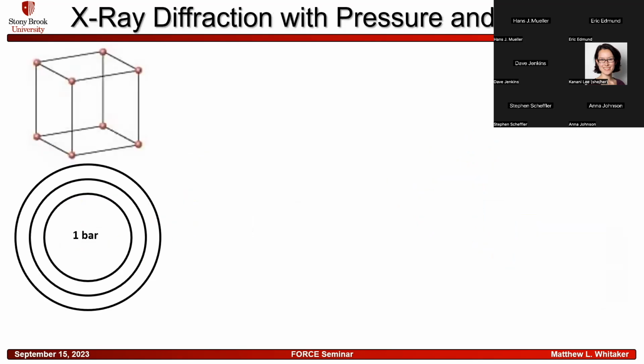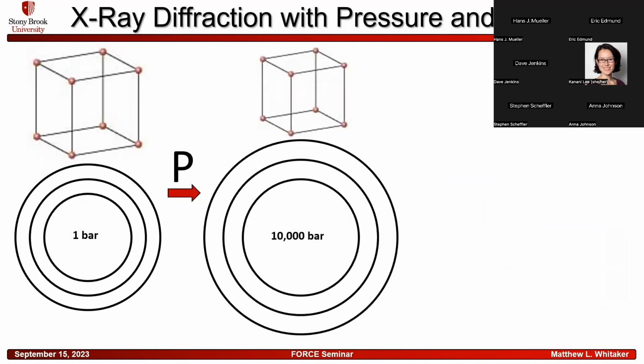So we have our sample that starts off at 1 bar, and it gives us a set of characteristic rings. Now we're going to add pressure. The sample is going to become smaller, which leads to the rings getting bigger in monochromatic beam, which took me a minute to really wrap my brain around, but that is the case because you're increasing the 2 theta, which is characteristic of a decrease in the d-spacing between the atomic planes.